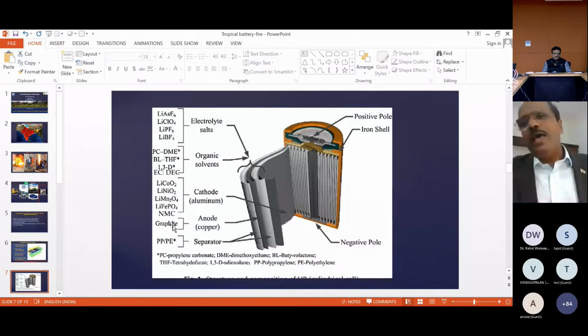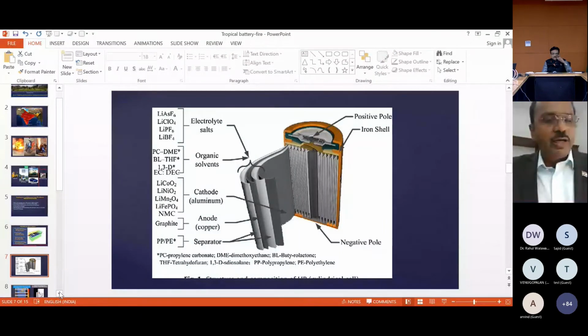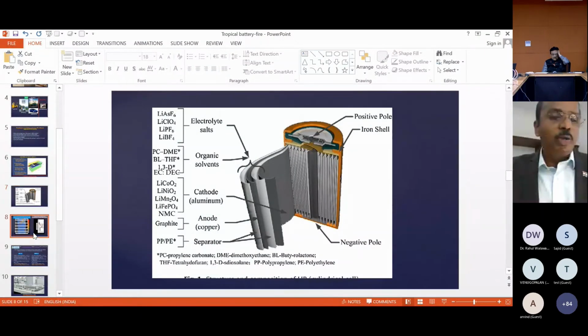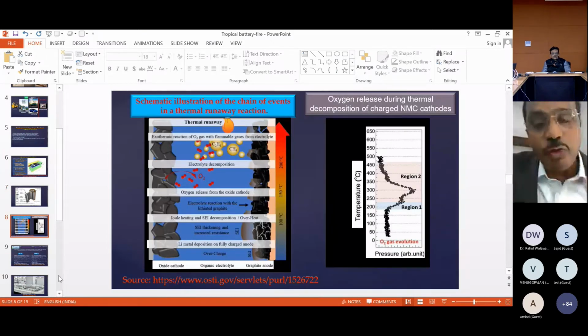And when all this is happening, graphite will also start burning, and then you have the separator, which is a polymer. So all these parts I'm showing are easy to burn the moment they see some temperature and the oxygen in the cell. So we are dealing with a situation that is very dangerous if you are not handling it properly. And you see this slide, the left side of the slide, look carefully. For each one I'm giving the source also, so that I'm not doing it by myself. It's all from the last one week. I've been accumulating data and seeing what best I can do.